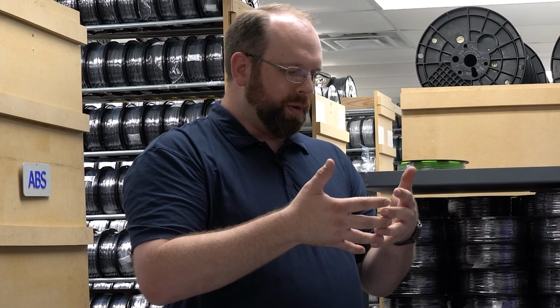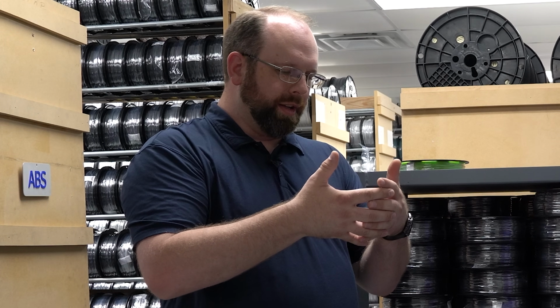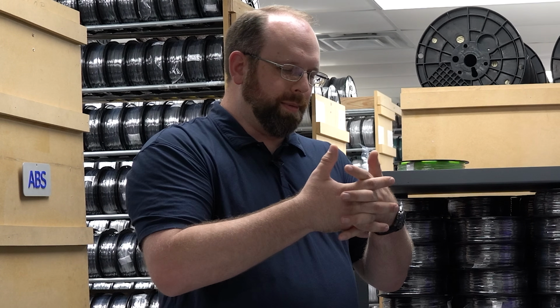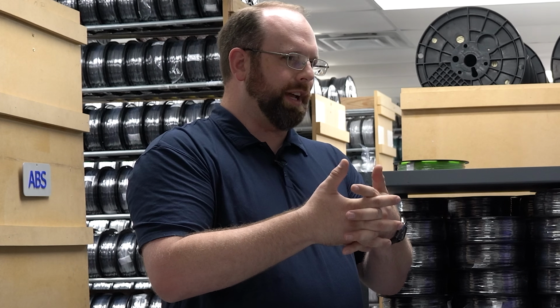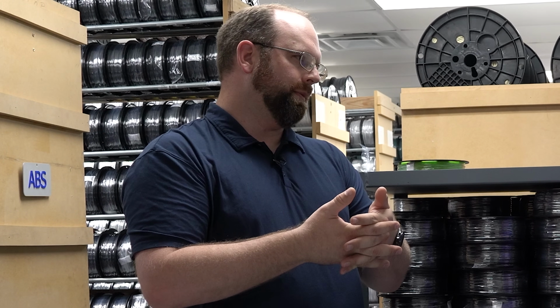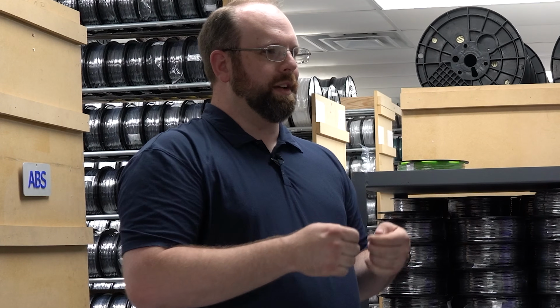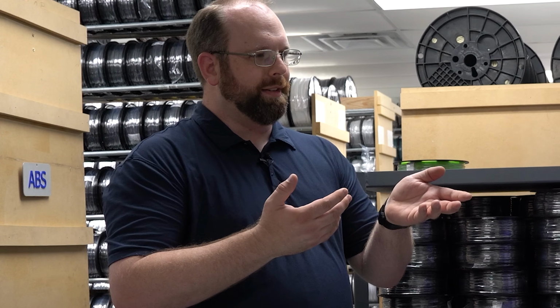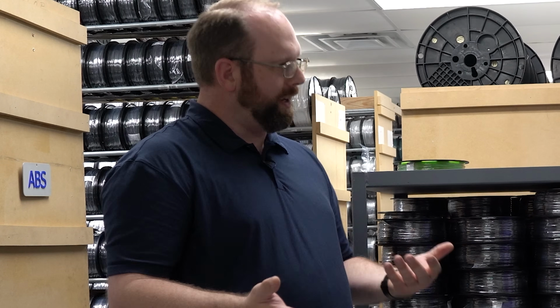And then when you slowly cool it after it's been in your dryer, then they lock even tighter than they did before, and it actually makes them stronger, so they're less inclined to craze. Okay. And so that's why you see, oh, I threw it in my dryer, now it's not brittle anymore. It's like, well, you annealed it, and that's great.